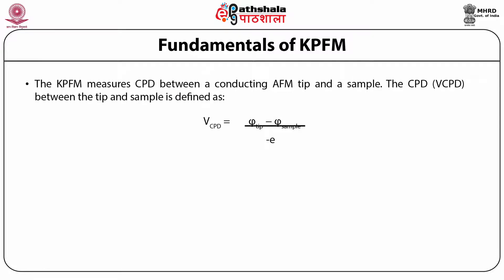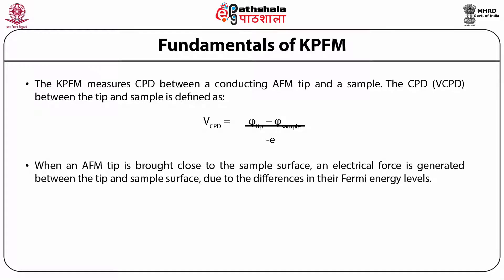Regarding the fundamentals of KPFM: KPFM measures CPD between a conducting AFM tip and a sample. The CPD between the tip and the sample is defined by a mathematical relation, where phi_sample and phi_tip are the work functions of the sample and tip, and e is the electronic charge. When an AFM tip is brought close to the sample surface, an electric force is generated between the tip and the sample surface due to the difference in their Fermi energy levels.